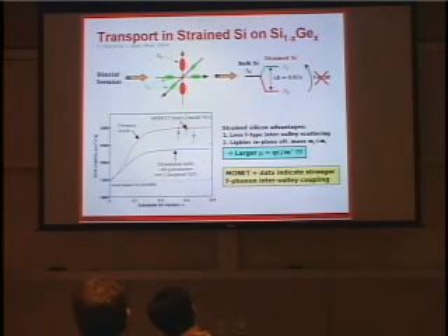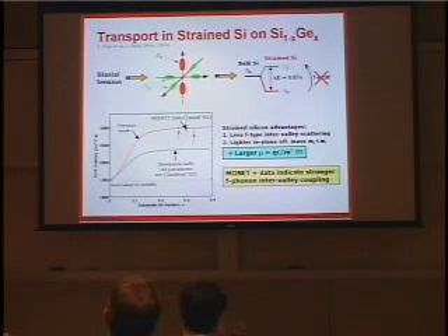And then the strain introduces a splitting, which is proportional to the amount of germanium in the substrate, to this fraction X of germanium in the substrate. A typical value for the germanium fraction is about 0.3. If you have X equal to 0.3 in the substrate, this energy splitting is about 0.2 eV. Now remember that the highest phonon energies available in silicon are about 50 to 60 meV, so 0.05 eV. So 0.2 versus 0.05 eV.